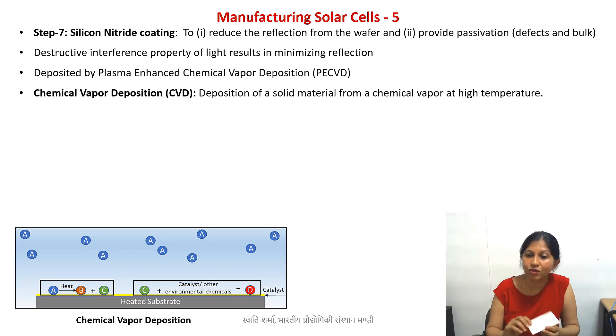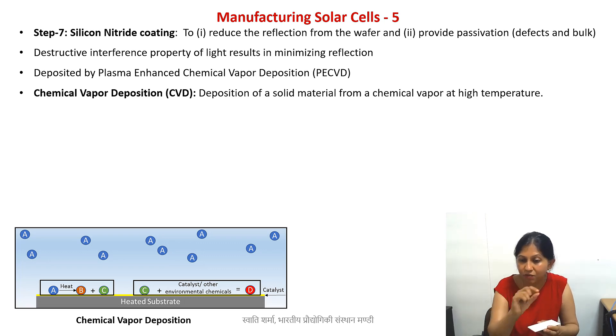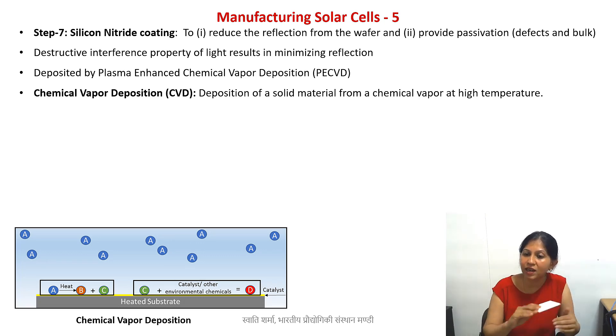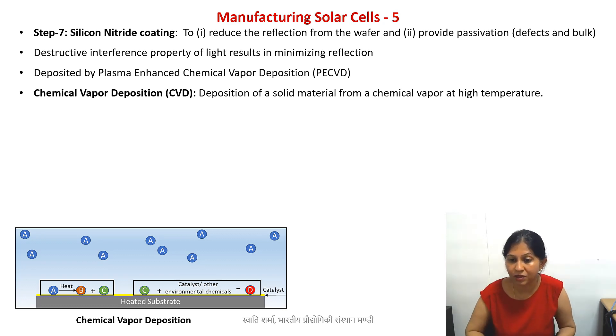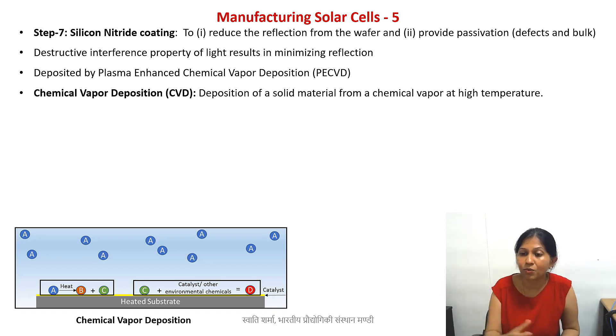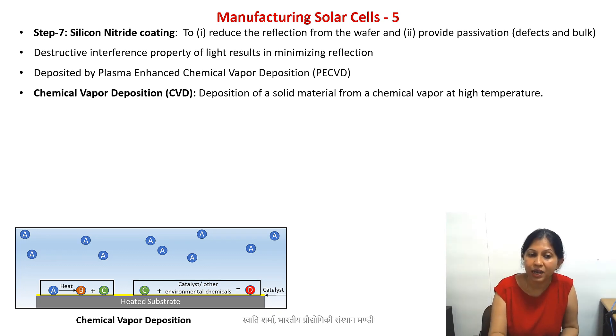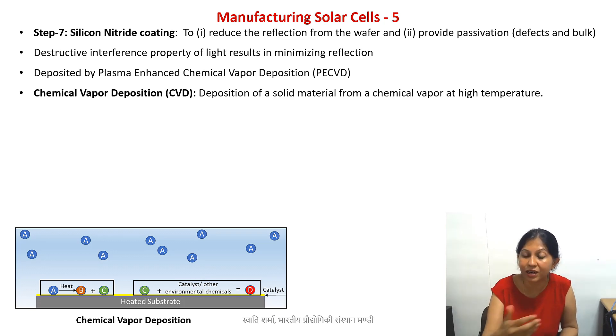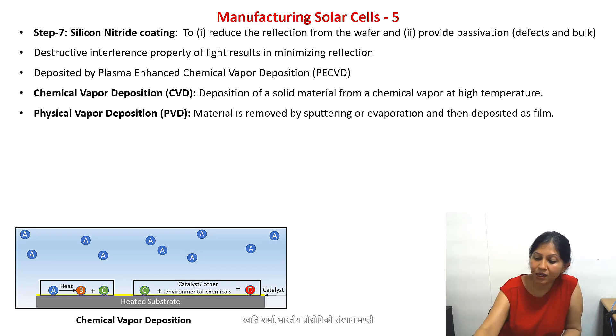We can control the precursor, control the temperature on the substrate, and also have thin catalytic films — as shown in the picture with a thin yellow film. By changing the type of catalyst, we can change the nature or the chemical composition of the film. This is CVD. It is done under high vacuum so no unwanted reactions occur. The vapors are diluted in an inert gas — nitrogen or argon, not oxygen — because oxygen would react.